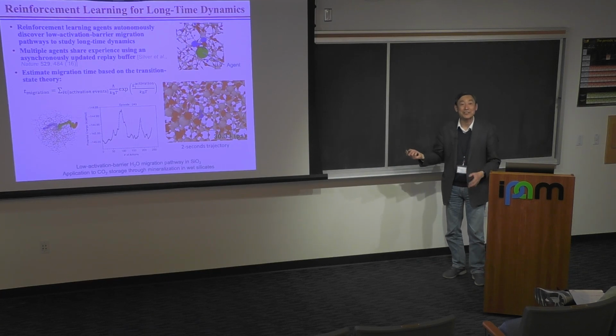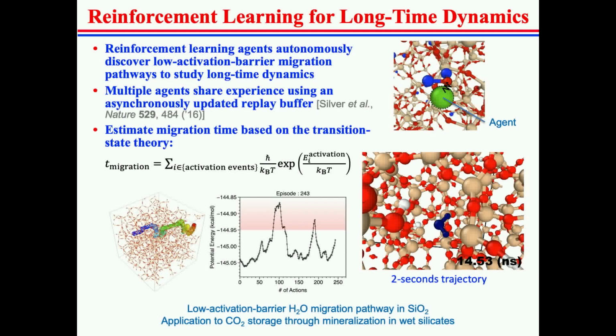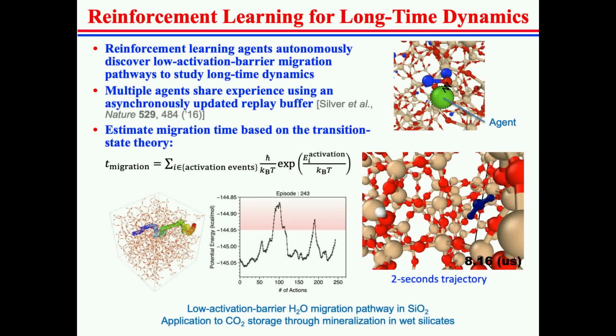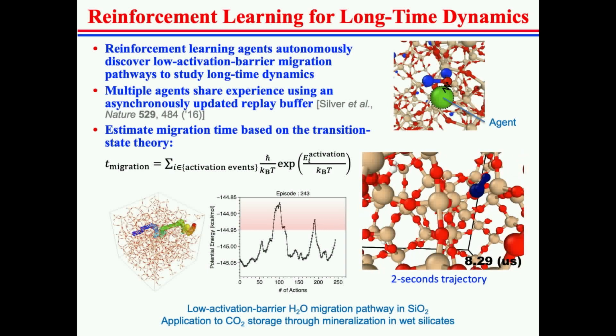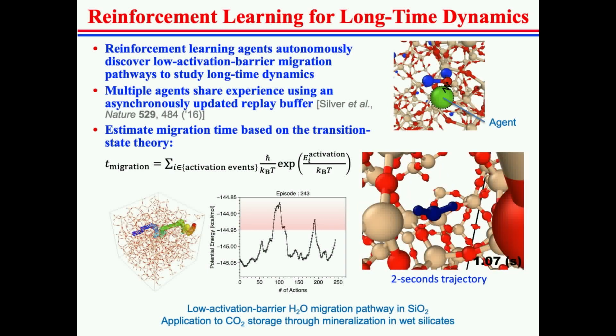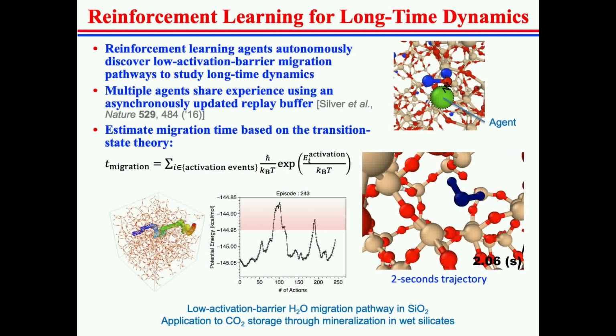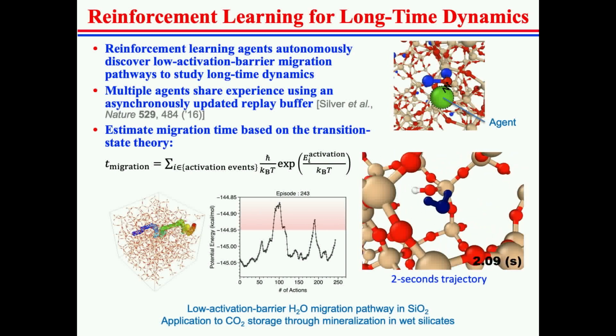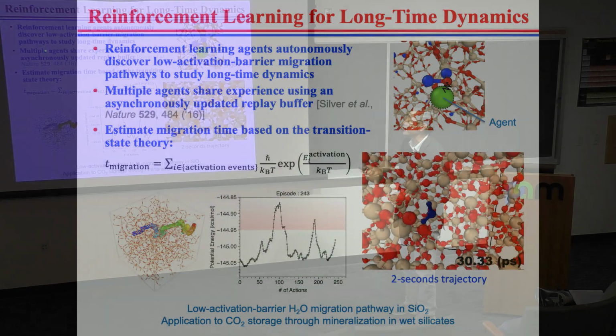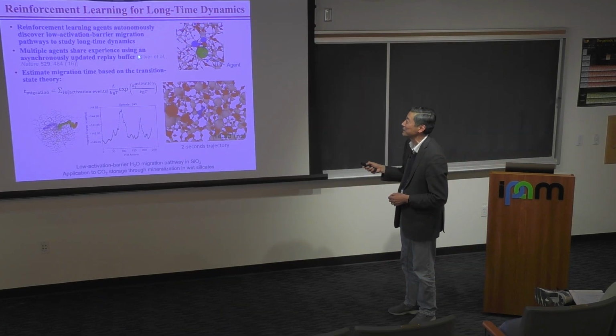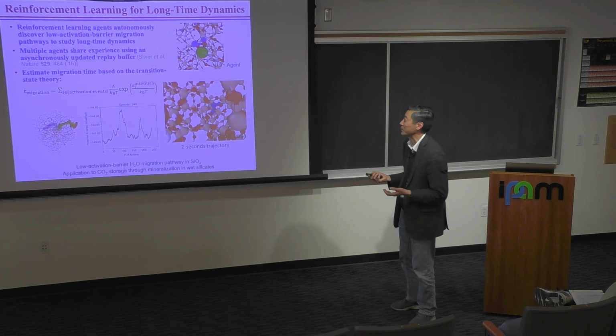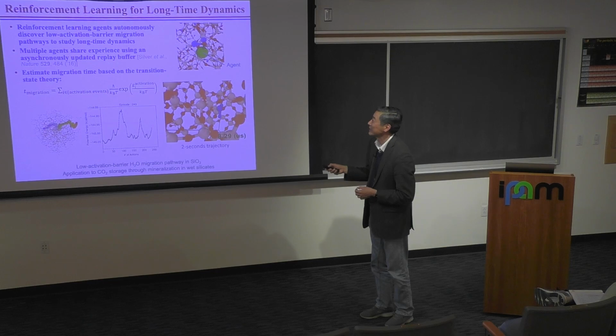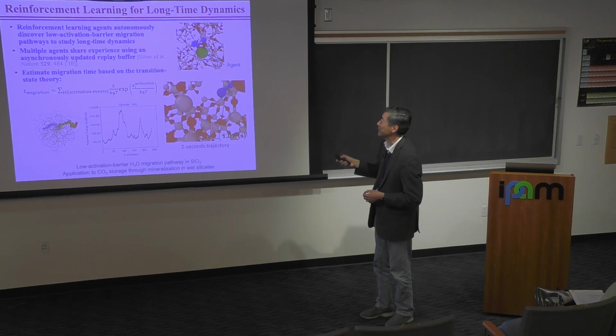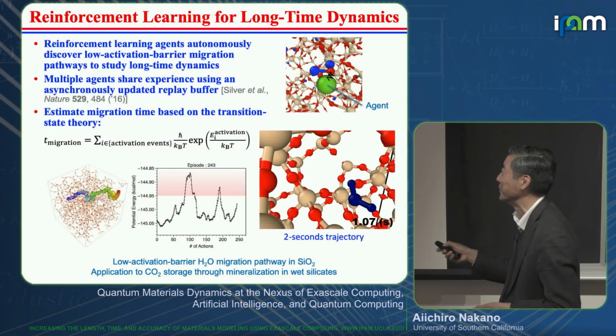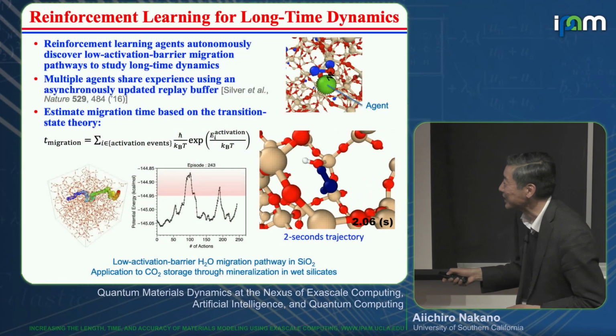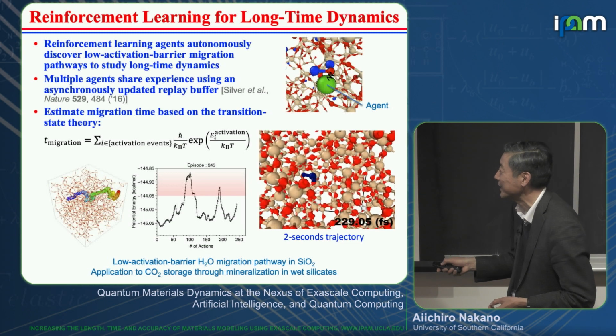But this is still nanosecond. The real growth is seconds or longer. So here again, reinforcement learning comes in. We use a reinforcement learning agent to autonomously discover low activation barrier migration pathways to study long-time dynamics. Here, multiple agents share a so-called replay buffer of experiments. They share experience to become smarter and smarter. Once the agent finds the migration path, we estimate the migration time using transition state theory. This is one of the migration paths of water in silica.